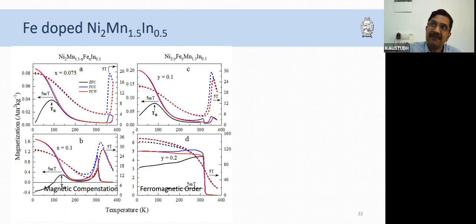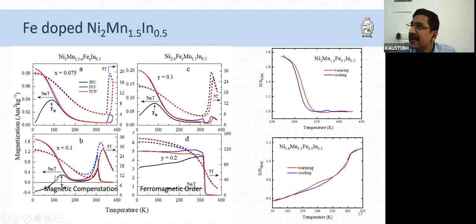So what has happened is that in MnFe there is a magnetic compensation, and in NiFe there is ferromagnetic order. Now we know from literature that whenever magnetic compensation occurs, there has to be another phase which is also magnetic that will polarize the spin of your main phase opposite to the direction of the applied field, and therefore you have this apparent negative magnetization. We also looked at resistivity, and in the case of MnFe, this was typically what you expect in the case of a strain glass material, whereas here this was a typical metallic behavior of a ferromagnet, and we could also see the ferromagnetic transition here.